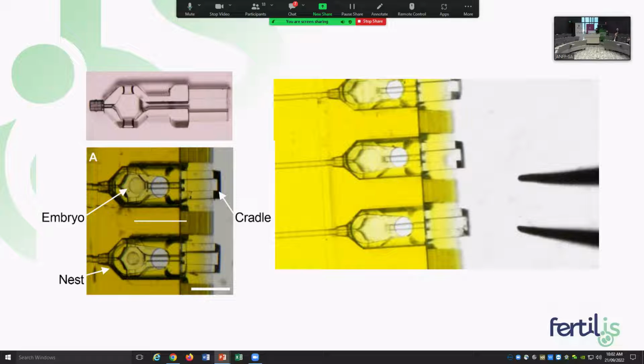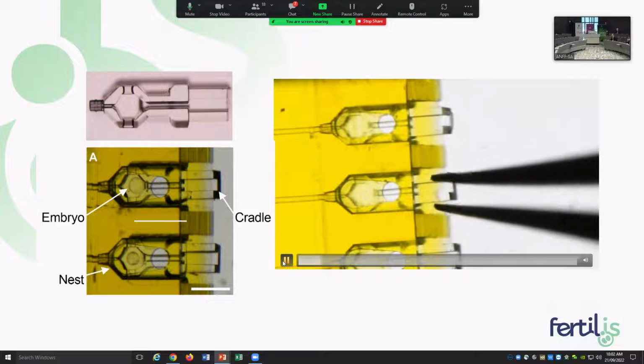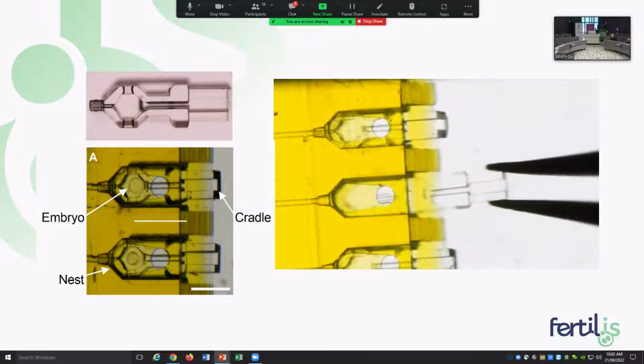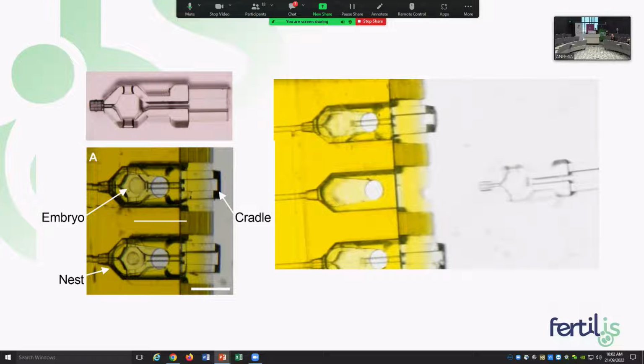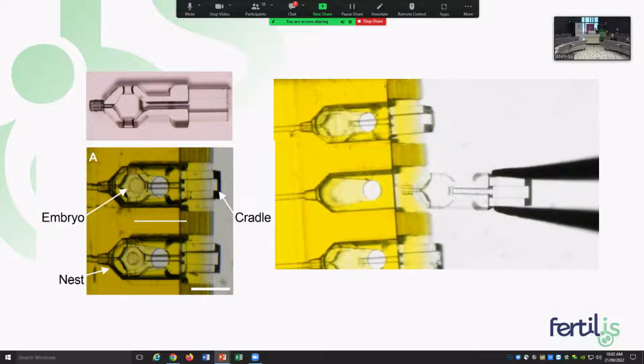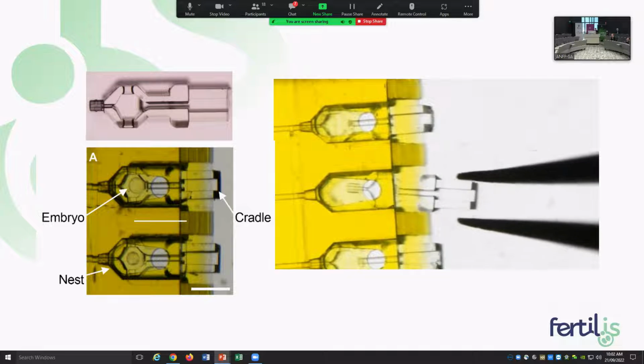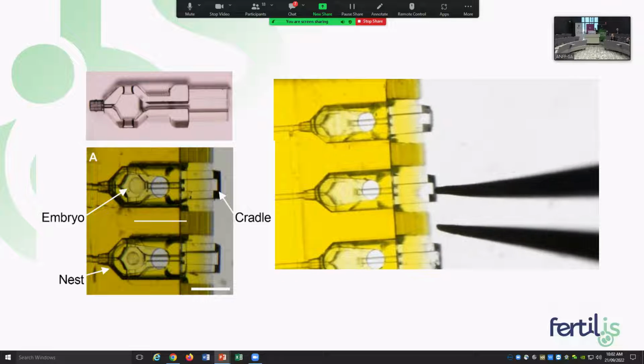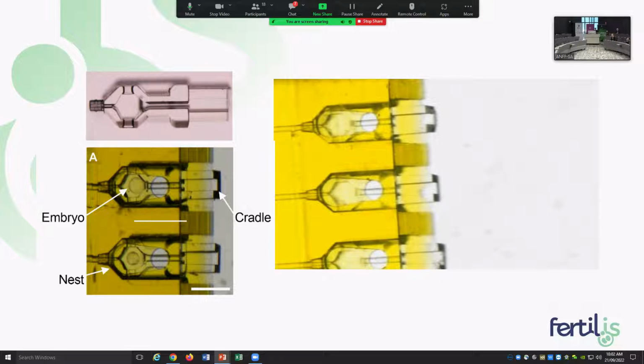Cradles were post-processed and developed by sequential immersion in 3 consecutive isopropanol baths and cured using a UV light. They were washed in an ethanol and detergent solution so that they were suitable for use with embryos and non-toxic. Just run a quick video showing our resident embryologist removing the cradle and then placing it back in. There's also an interlocking feature which holds the cradle in place, again at an incredible scale.